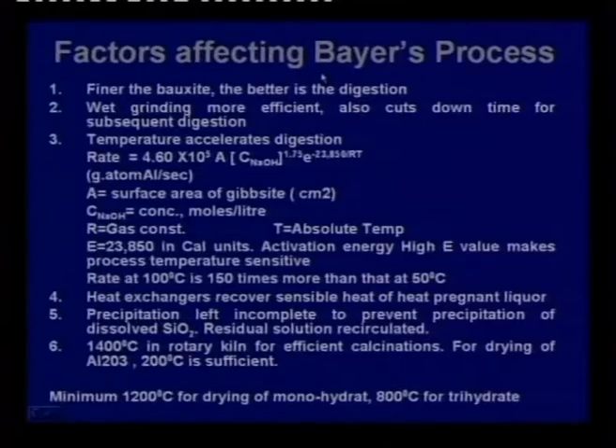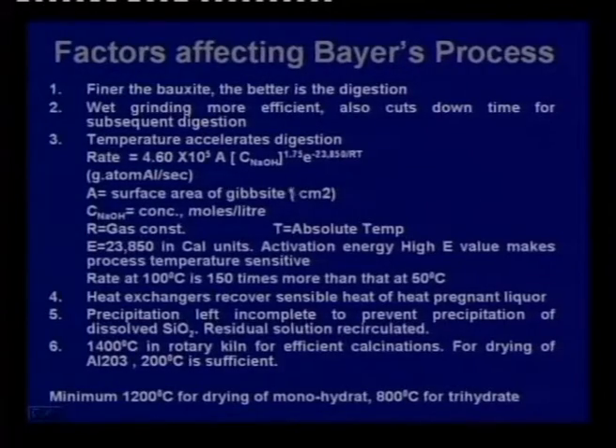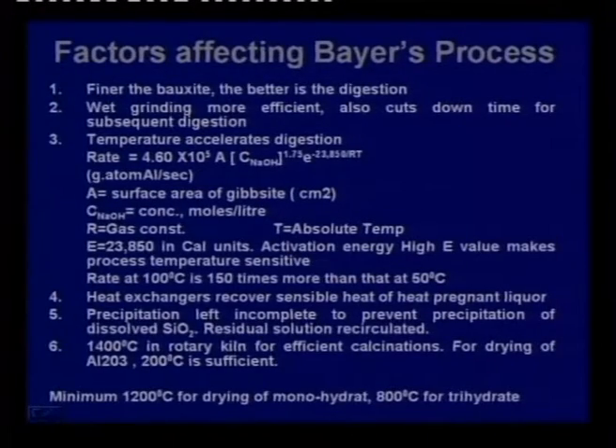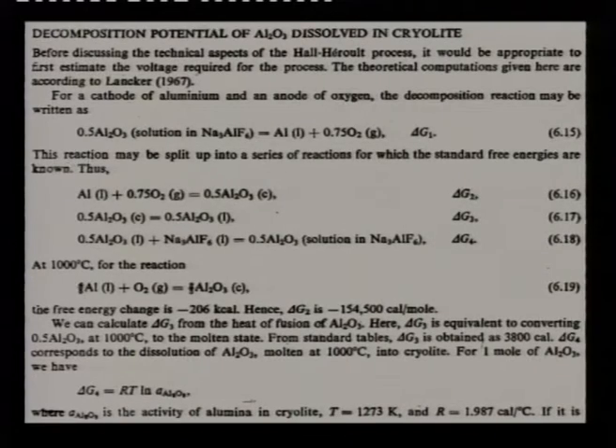The key to aluminum extraction is Bayer's process, which produces pure alumina. It depends on many factors. Some of them have been considered: particle size, concentration of leach liquor. People have come out with an equation for the rate of leaching. Temperature should be high, and sometimes leaching operates at 220 degrees. You need a lot of pressure in an autoclave. Some people would rather settle for lower temperatures, because autoclave operation at higher temperatures means more expensive equipment and more energy. So the different companies have different ways of doing it; no two companies act in the same manner. Eventually, everybody tries to produce pure Al2O3, which will go into an aluminum cell.